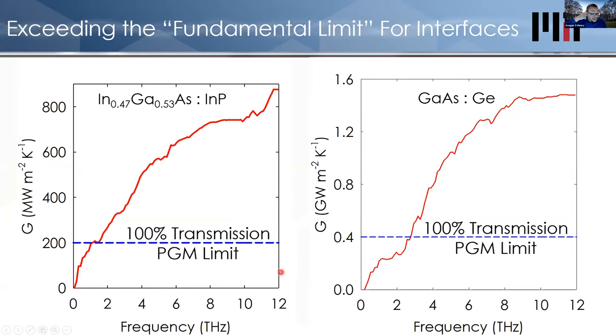One of the other non-intuitive things that came out of this is when you think about interfaces, there was a bunch of theory where, when you have an interface, the idea was you have a particle that's going to bounce off the interface and it's got some probability of being reflected or transmitted. In essence, we think that physical picture is flawed. If there's a probability of scattering, then that probability is bounded by one, right? The most you could ever transmit is 100%. If that's true, then there would be an intrinsic upper limit on the conductance you could ever get between two materials. And in the experimental data, we have confirmation in this system that here's the 100% transmission limit. We've shown that there are materials that exceed this limit, and our theory predicts a value quite a bit higher than this 100% transmission limit. And this is a great indication that, again, the theory itself has a problem.